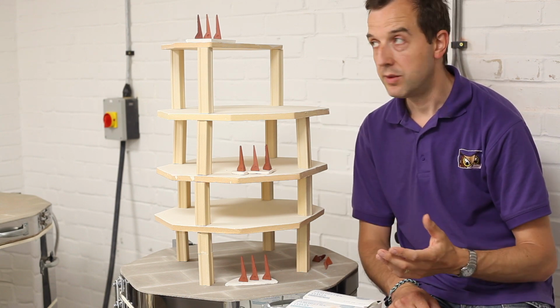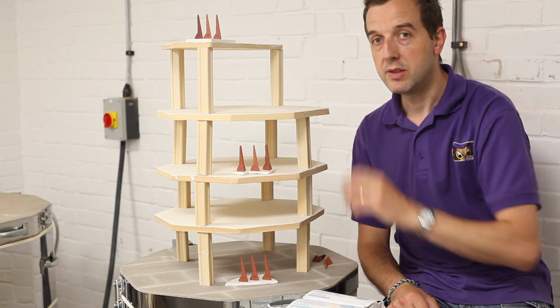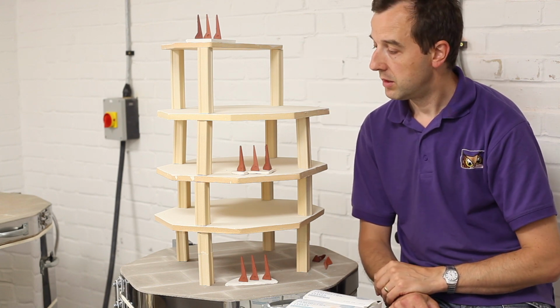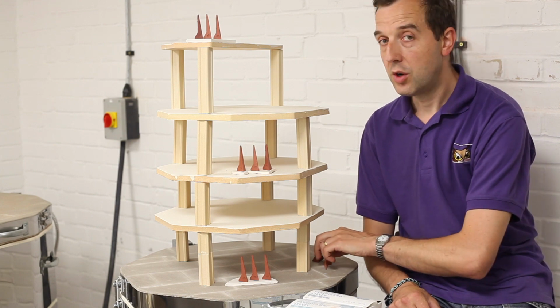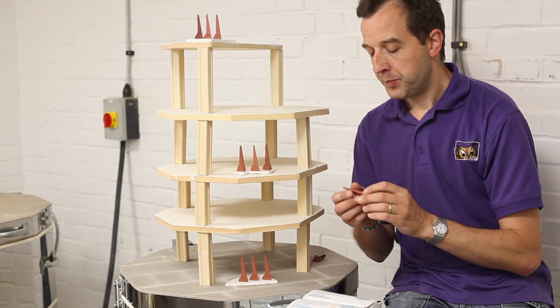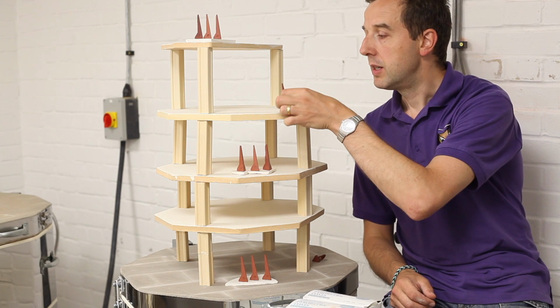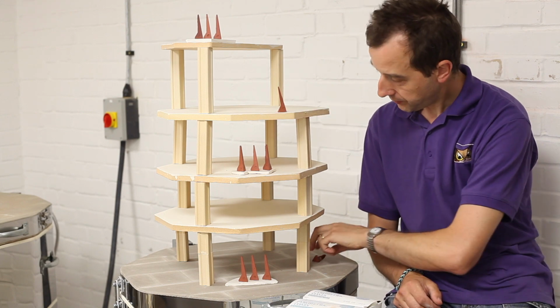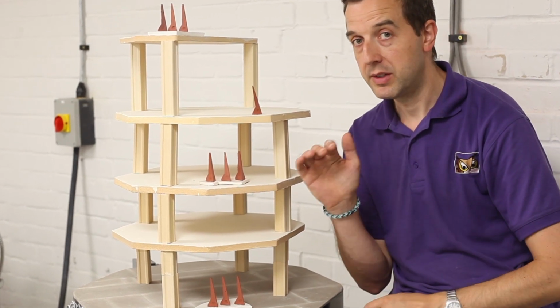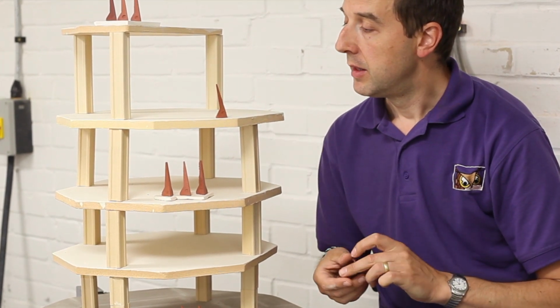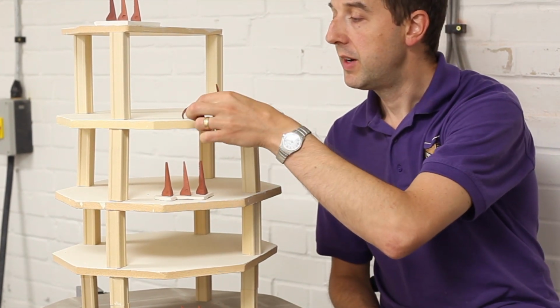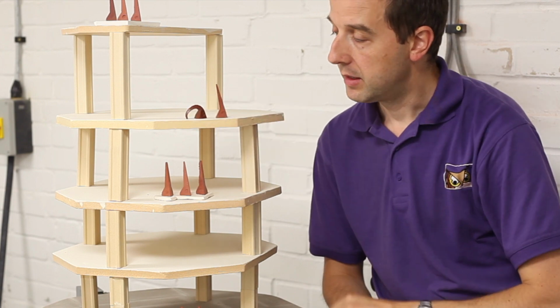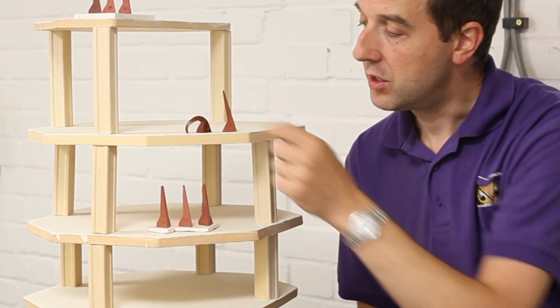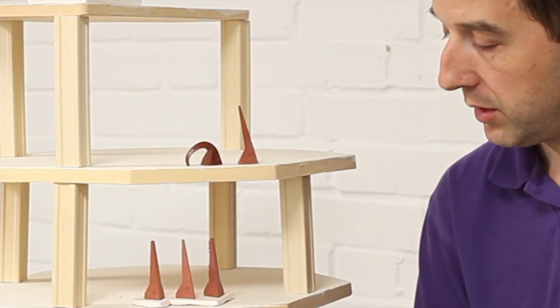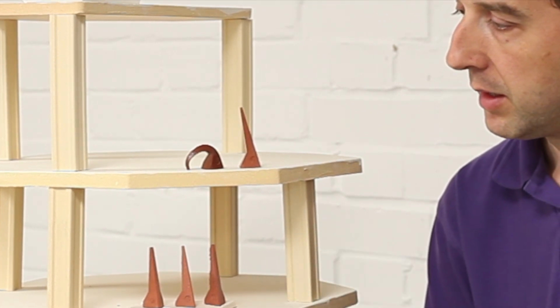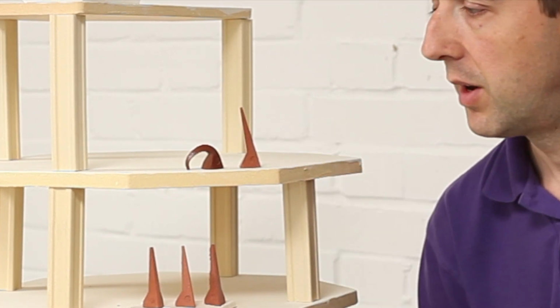And when you come to unload the kiln, have a look and see what the difference is between each of those layers. What you're hoping to find is your 05 cone should still look like that. It shouldn't have moved because we haven't gone to a 05. The 06 in a perfect firing should look like that. The tip should just bend over and just touch the surface of the kiln shelf or the bisque that it stood on. That indicates a perfect 06 firing.